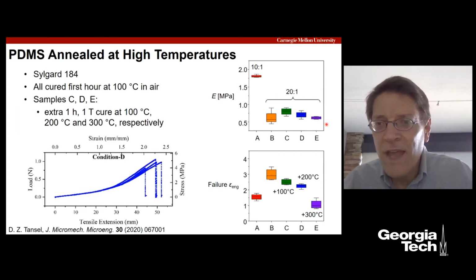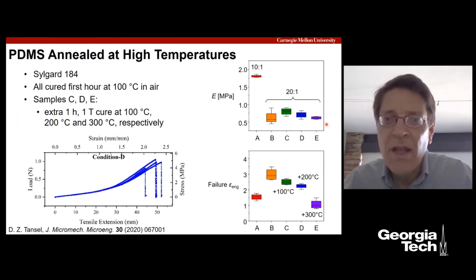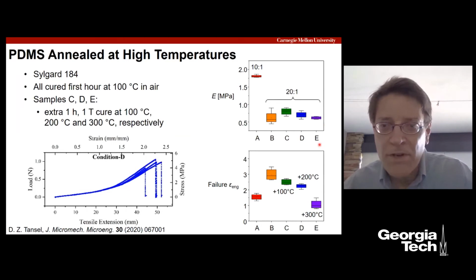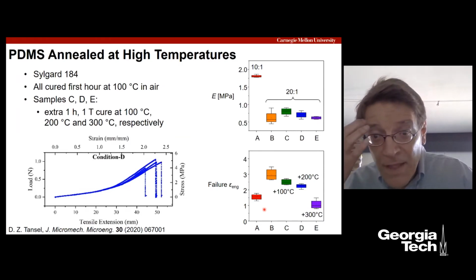And we think that has to do with decomposition of the material. Obviously there's no oxygen, so we're not affecting the bonds with oxygen, but probably effectively burning some of the material to make it a little weaker. What's interesting is the strain to failure, that we were able to get reasonable strain to failure. Even at 300 C, the strain to failure was on the order of 100%.